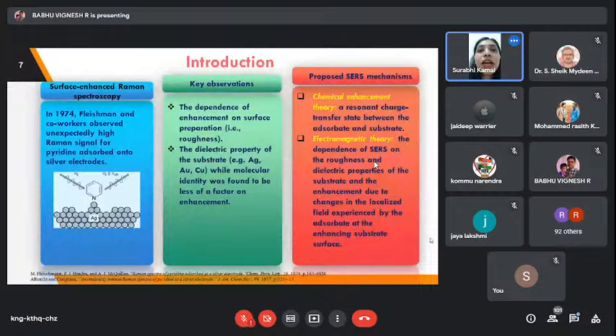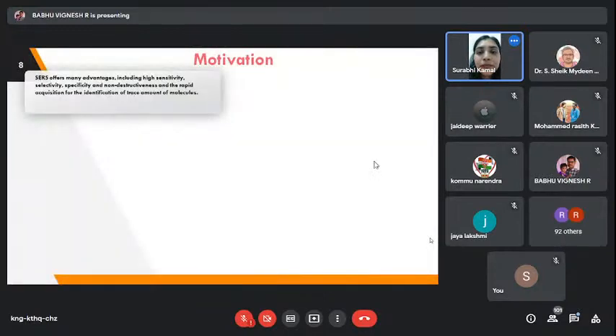And there was also a property which is directly connected to SERS, that was the dielectric property of the substrate, such as the metals that are used for these substrates, which were commonly silver, gold, and copper, while molecular identity was found to be less of a factor on the enhancement. And for surface enhanced Raman spectroscopy, one was the chemical enhancement, and second was the electromagnetic theory. So the chemical enhancement theory talks more about SERS on the roughness and the dielectric property of the substrate, and the enhancement due to the changes in the localized field experienced by the adsorbent of the enhancing substrate surface.